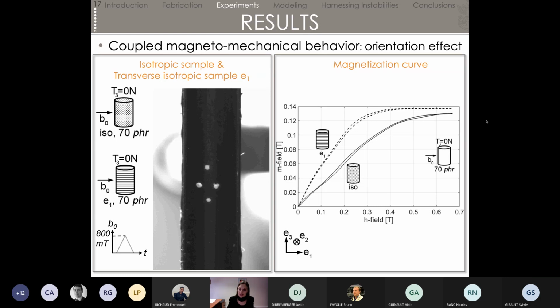What we see also that's interesting is that we do not attain saturation. And in fact, if we were pushing the magnetic field more and more, we would end up with an instability, which means so far we had magnetostriction, but we're not at saturation for the sample. If we put more magnetic field, the whole sample will end up rotating with the compass effect to align itself with the magnetic field. So we had magnetostriction, but it is not a magnetostriction that will last for any applied magnetic field.